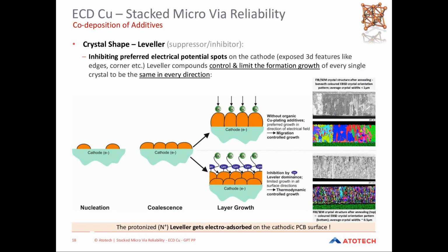The plating process itself, you already know, uses several different organic compounds: leveler, brightener, carrier, and additionally we also need chloride as a complexing agent in these electroplating processes. And here you find a short introduction to how the adsorption takes place when nucleation starts on the interface of stacked micro vias. First of all, you see here an image on top of how the copper crystal nucleation will start without any plating additives.